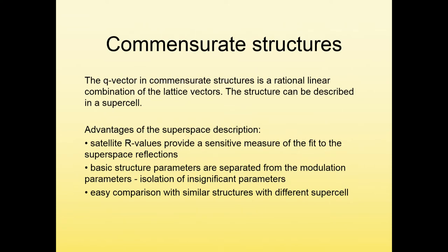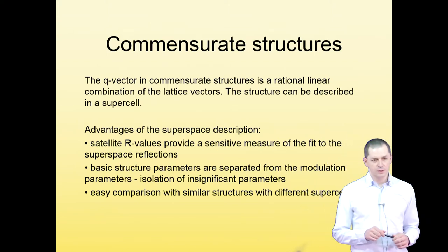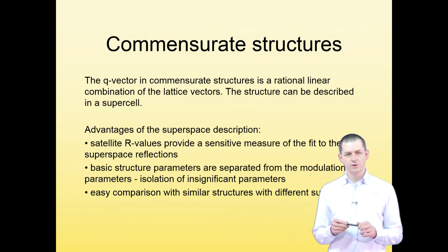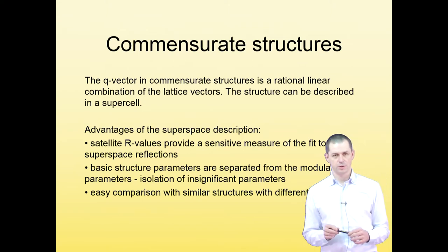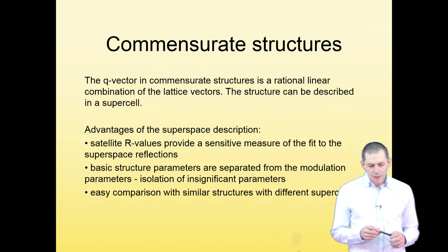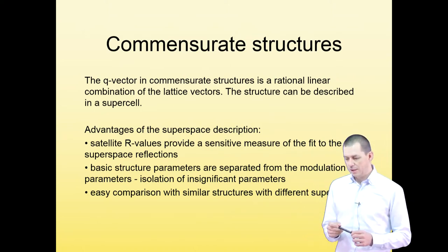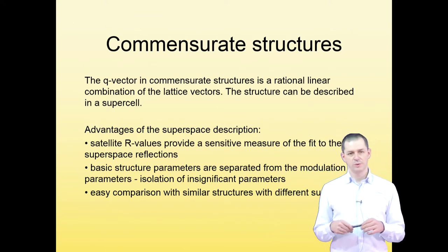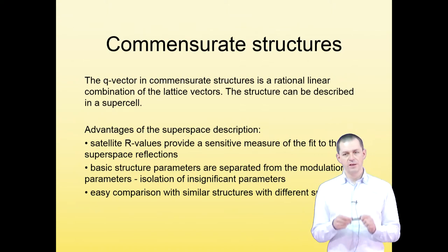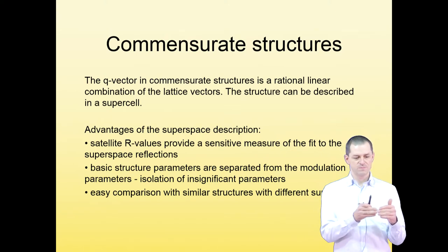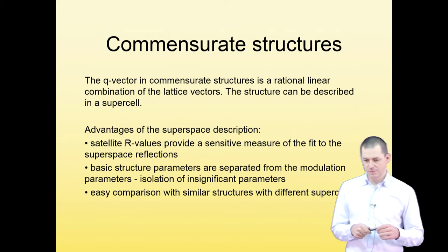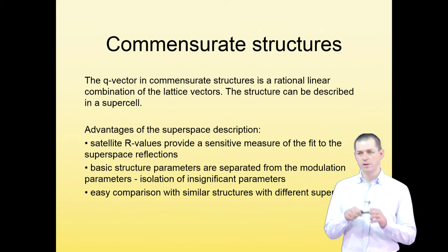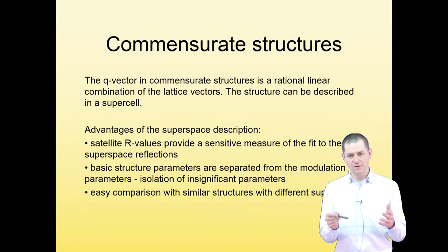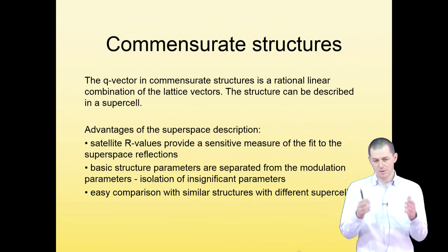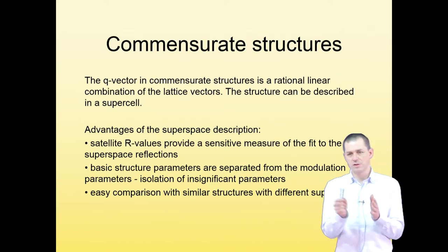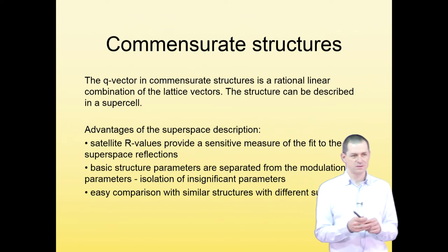Before I stop, I need to mention another important class of structures which are related to incommensurately modulated structures, but they are not incommensurate. They are called commensurate or commensurately modulated structures. In truly incommensurate structures, the modulation vector has components which are incommensurate with the basic periodicity. So ideally, the ratio between the coordinates of the modulation vector and the reciprocal lattice vectors should be irrational. You can never say if a certain modulation vector has really irrational components, because the measurement has finite precision, so there is always a rational number within the precision of your experiment that you can find.